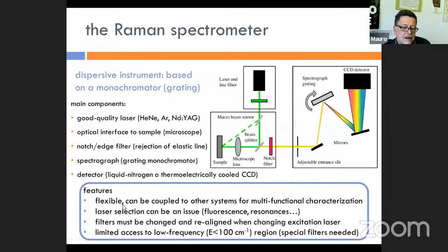So this kind of system is rather flexible because it can be coupled to other systems like atomic force microscopes. It can be put inside the electron microscope. On the other hand, laser selection is a delicate issue because the laser must be carefully selected according to the sample. And when changing the laser, the filters must be changed. So if you have several lasers, you need several sets of filters because they are specific for the laser frequency. And finally, in general, this system doesn't allow measurement of the low frequency Raman region. You need a different kind of filters which are rather expensive.